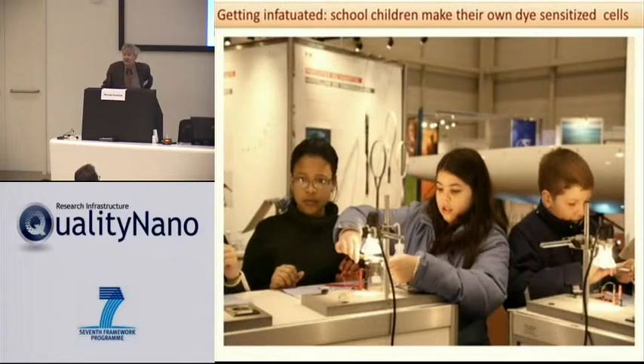Well, to be honest, rutile works pretty well. It has a little bit of a lower band gap, so we are getting to a 3 electron volt band gap, which means it picks up light at 420 nanometers, which is not something you like, okay? And it also tends to be in a needle form, and we're a little bit worried about inorganic needles for reasons which you can guess.